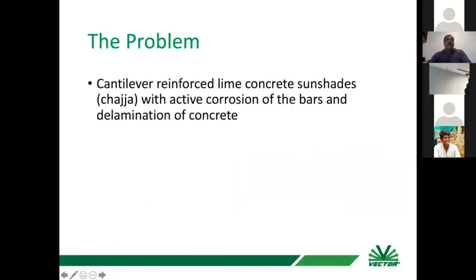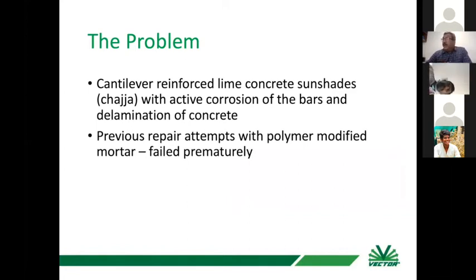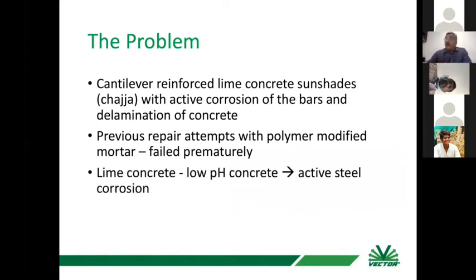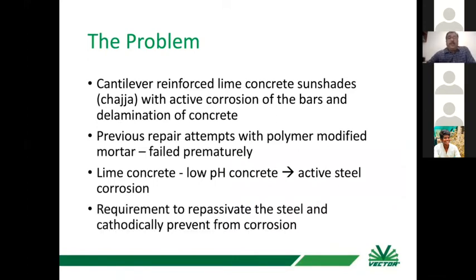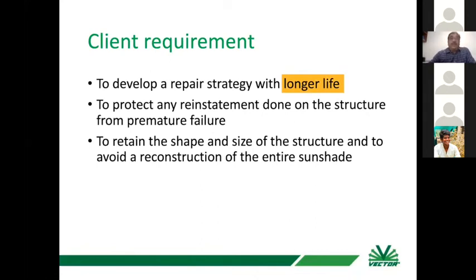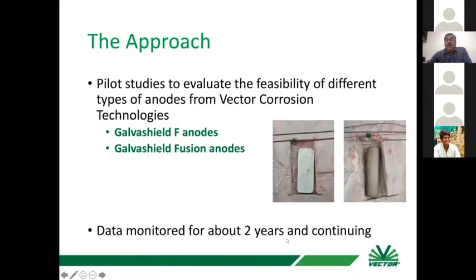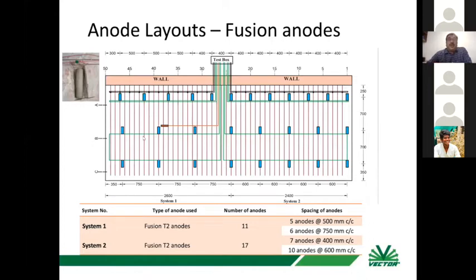So to develop that system, we carried out one pilot project wherein cantilever reinforced concrete sunshades with high corrosion of rebar and delamination of concrete were there. And earlier repair had been done, but it failed prematurely. And lime concrete was there. It was not cement concrete. So it was difficult for us to design the system. But we tried the pilot project with various options, and we found it successful. We developed a system which has a longer life to protect any reinstatement which has already been done from premature failure and retain the shape and size of the structure to avoid the reconstruction of entire elements. We used different types of anodes, and we did monitor for 2 years. This was the design, how the anodes have been installed.